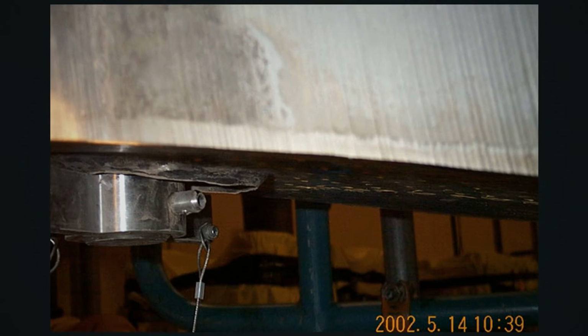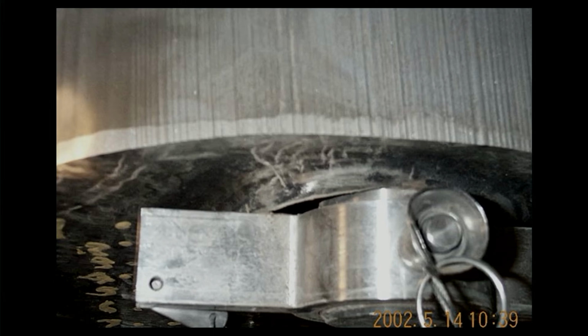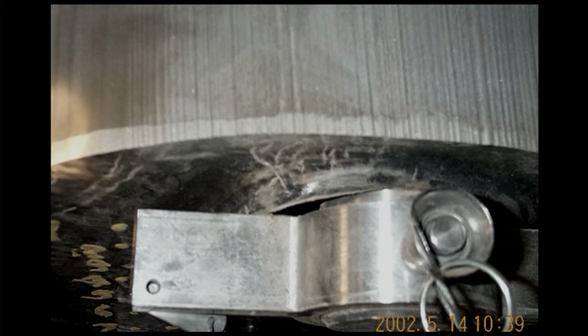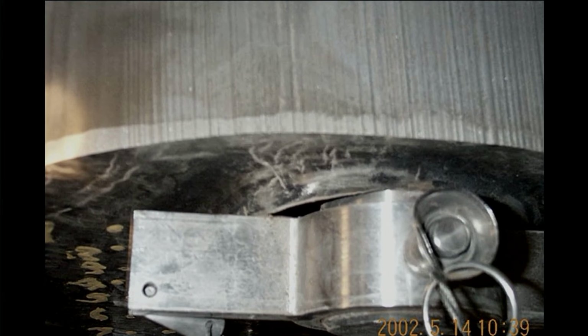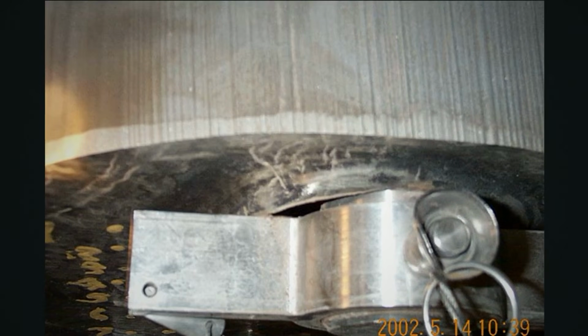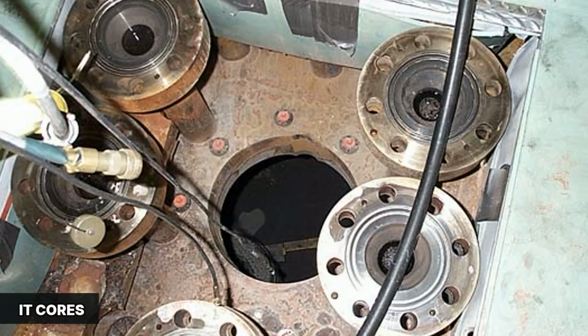Concentrated boric acid at temperature attacks carbon steel aggressively. It converts steel to iron borate and iron oxide, the red-brown material that showed up on those filter elements. The corrosion product does not seal the wound. It flakes and washes and gets carried off, exposing fresh metal underneath. The reaction has a continuous supply of acid, a continuous supply of heat, and a continuous supply of new steel. So the wastage does not slow down.